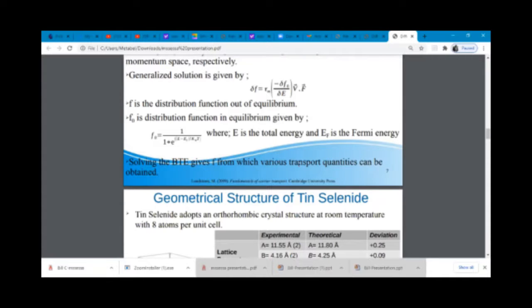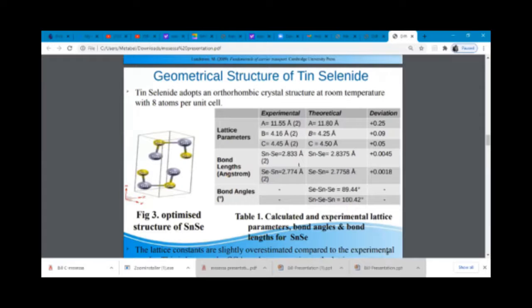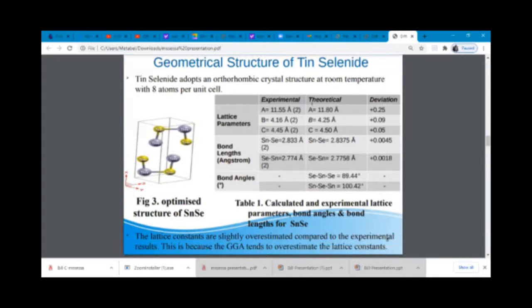So let me go to the results. This is the structure of tin selenide, the relaxed and optimized structure. It's an orthorhombic crystal structure at room temperature with 8 atoms per unit cell. The lattice parameters, bond lengths, and bond angles obtained in this work against the experimental values are shown in table 1, and the deviation.